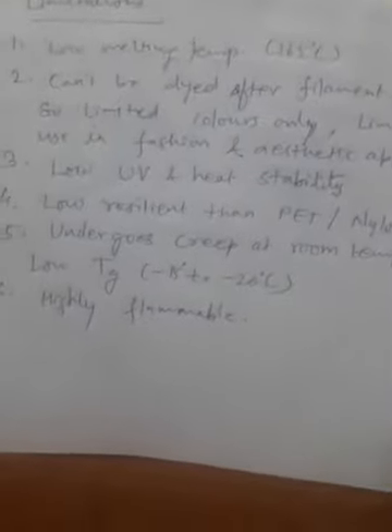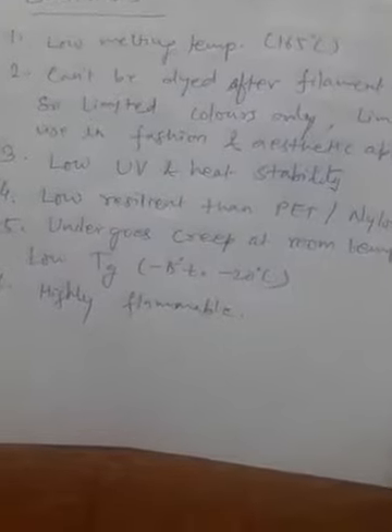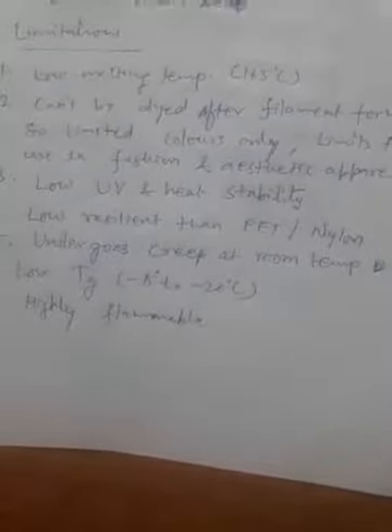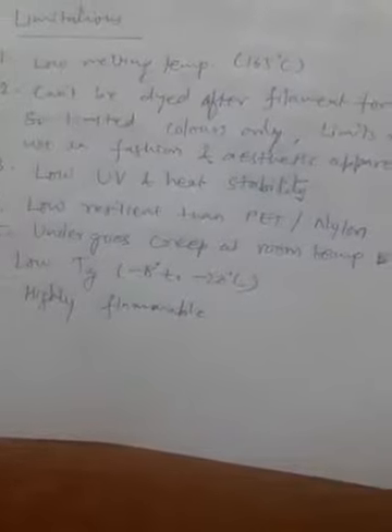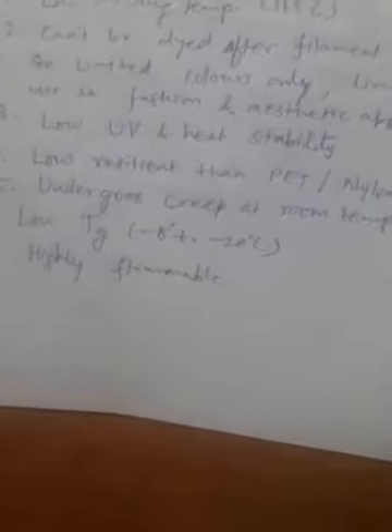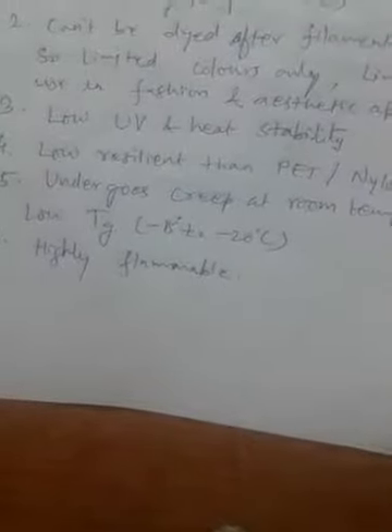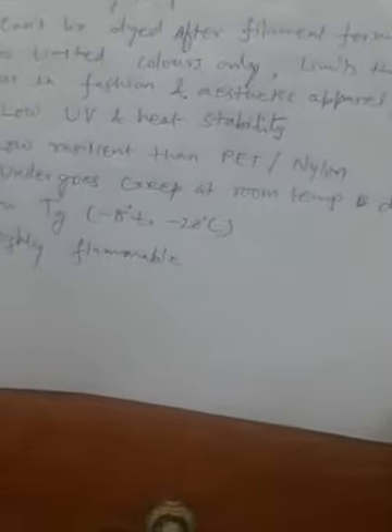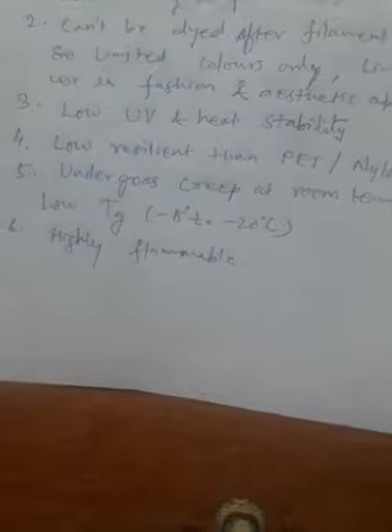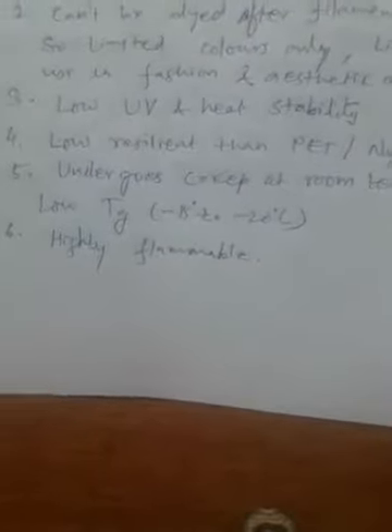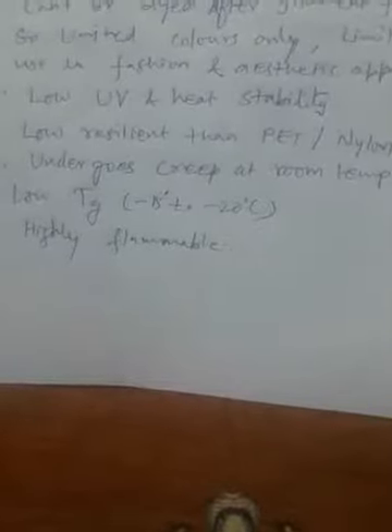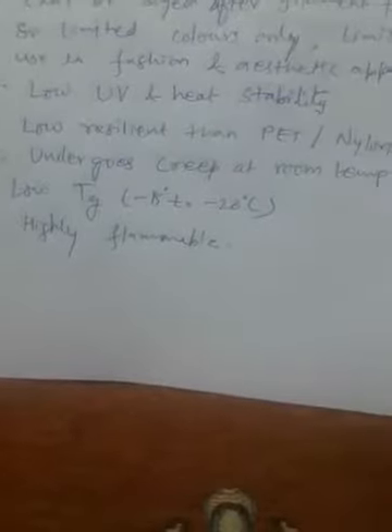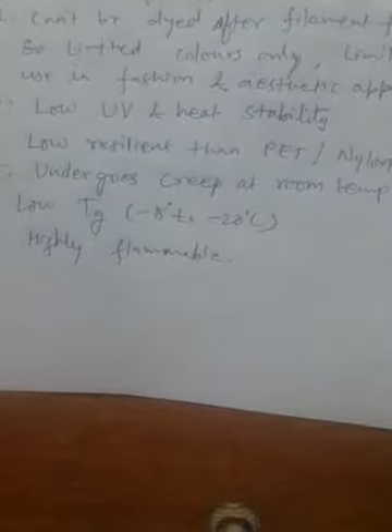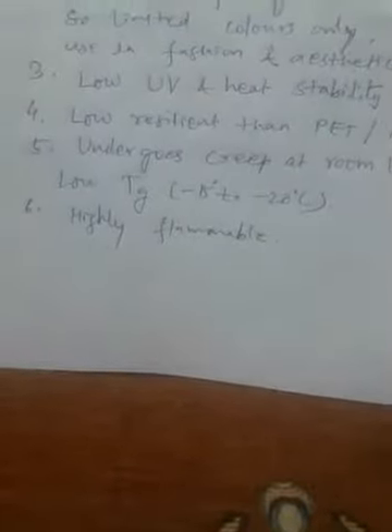But some limitations are also there. Its low melting temperature is one of the biggest limitations of this fiber. It can't be dyed after filament formation, meaning only master color batch pigmentation is there, so it limits the applications in fashion and aesthetic apparel garments. Also low stability against UV light and heat, and low resilience compared to PET and nylon. Low resilience means its bulk properties as compared to polyester and nylon are slightly lower, and because of low Tg, sometimes even at room temperature it undergoes creep behavior, and again the highly flammable nature of this fiber.